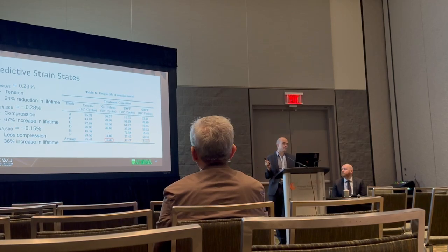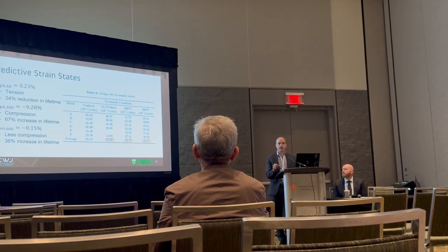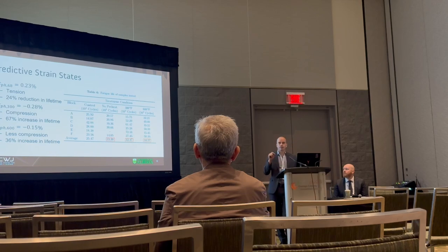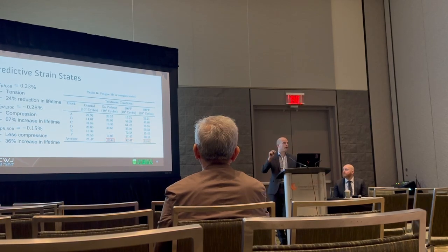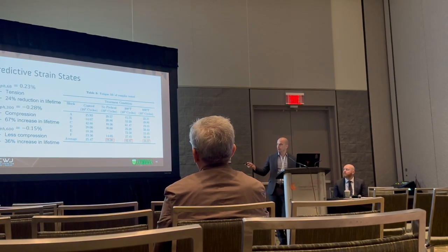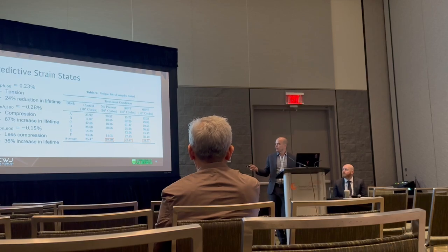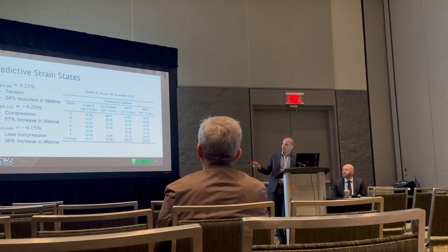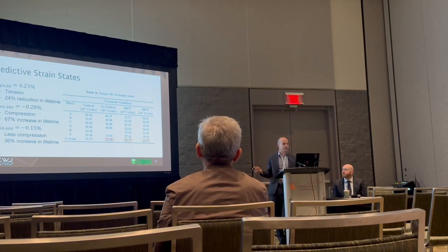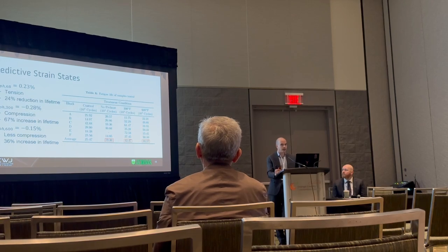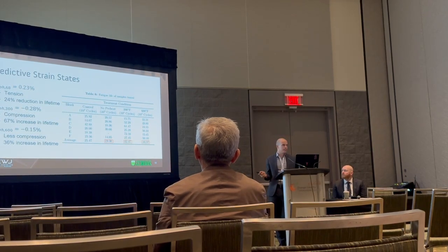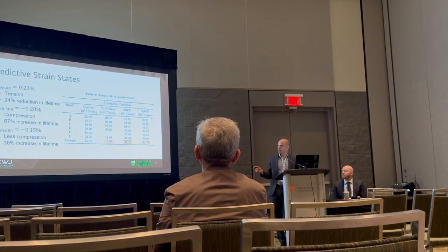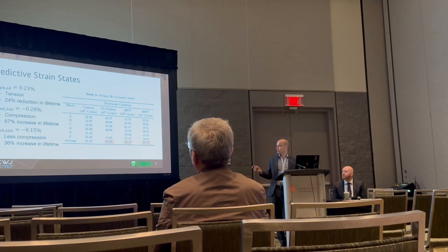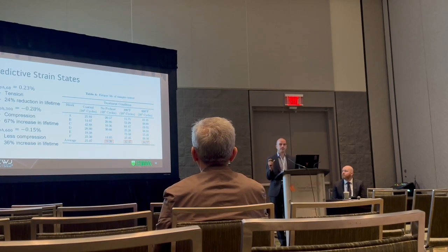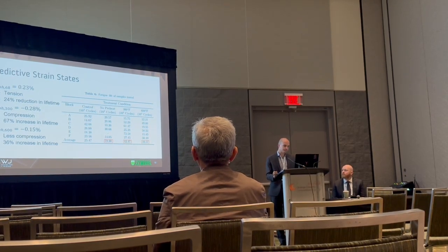But what really surprised me when we started running these numbers is for the 600 degree case, I used the data out of JMatPro to find what percentage of martensite transformation we were at, like how far had we proceeded when we hit that equilibrium at 600 degrees. Well, it's about half of the 300 degree case, and sure enough, the increase in lifetime is about half as much. So using this very simple, just slope-based model, I'm predicting with pretty good accuracy what the improvement in fatigue life under the same alloy would be.